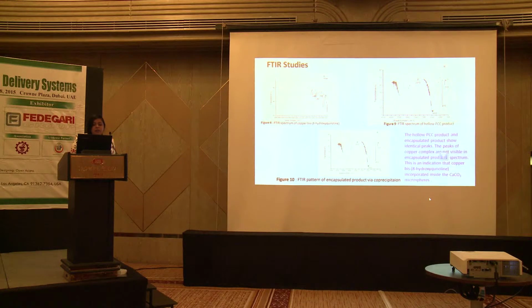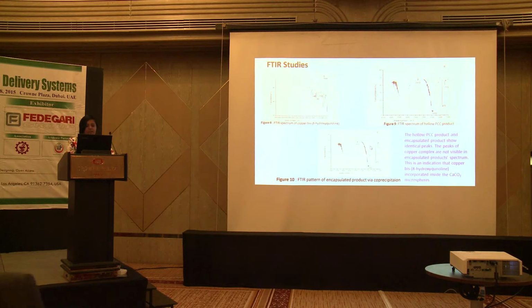The same kind of result was observed in the FTIR study. This is the pattern of the drug. This is the pattern of the hollow precipitated calcium carbonate product, and this is the encapsulated product. So both peak patterns are the same, but the peaks of the drug are not visible in those two. So this indicates that the copper complex is incorporated inside these calcium carbonate microspheres.